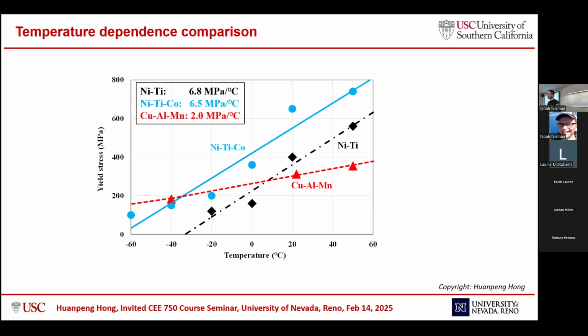And for copper aluminum manganese alloy, it's only around 2 megapascal per Celsius. That means this material is more stable at different temperatures. As the temperature reduces, its yield stress does not reduce much.